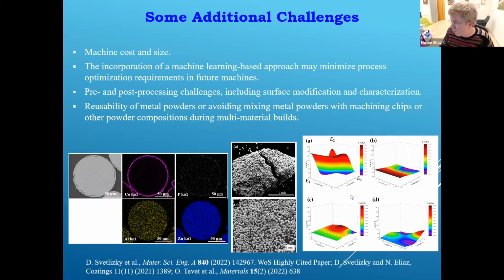And finally, before taking your questions, on the right-hand side, sometimes we have samples that we don't want to make into ASTM dog-bone samples. So we are using the dynamic pulse echo technique, for instance, to measure the elastic constants of the material. We can construct the whole tensor of elastic constants, and then we combine it, of course, later with tensile tests to get the yield point, UTS, and so on.